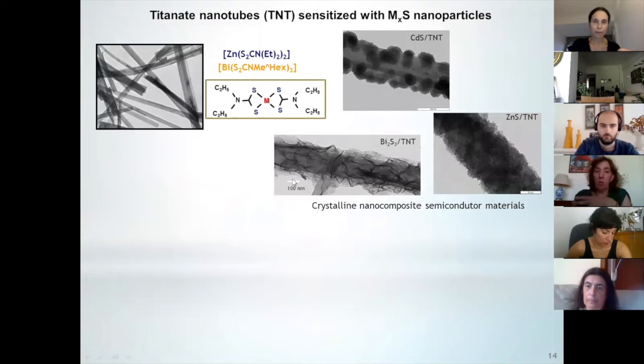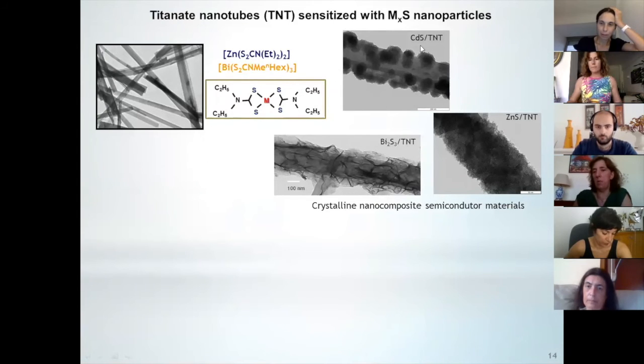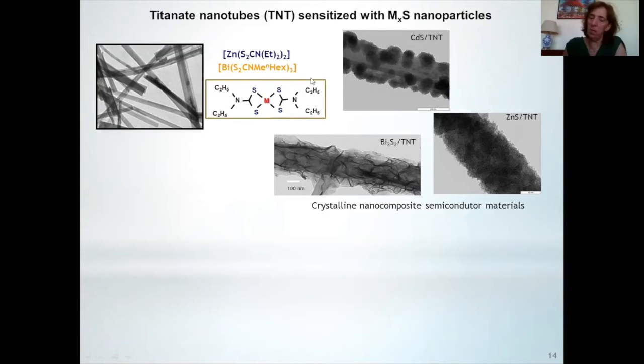We can also think about modifying these materials with some other semiconductor nanoparticles. For instance, some metal sulfide nanoparticles, using, for instance, a unimolecular precursor for the degradation and to obtain the sulfide materials. And as you can see here, depending on the metal, we are able to have nanocomposites with very different morphology. I must say that here, these are small islands with very, very small crystallites of CdS.